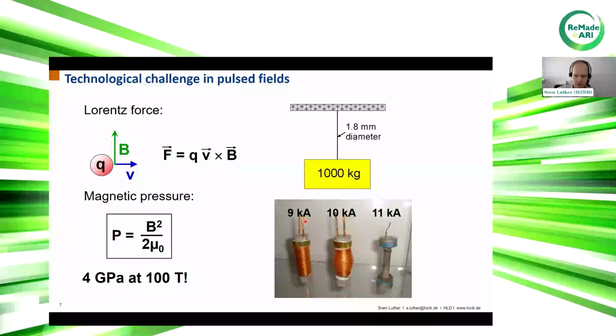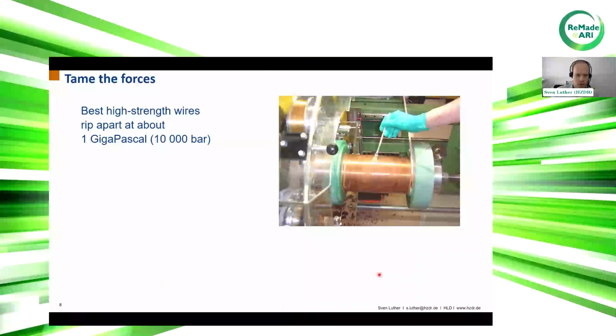And then they also made some experiments to show how this would act if you just change the current. At 9 kiloamps, you see the coil is still alive. But at 10 kiloamps, you can already see how this coil is blown up, because these forces are acting to the outside. And if we go to higher currents, at 11 kiloamps, you see the whole coil is already fragmented. And to overcome these forces, we have to tame them, because the best high-strength wires hold about 1 gigapascal, which is 10,000 bar. Ambient pressure is roughly 1 bar. You see there's lots of pressure acting on these wires.